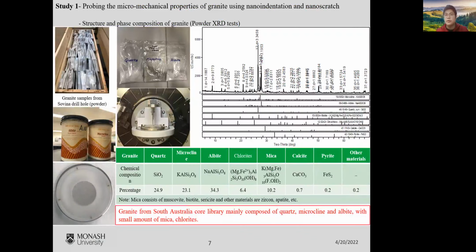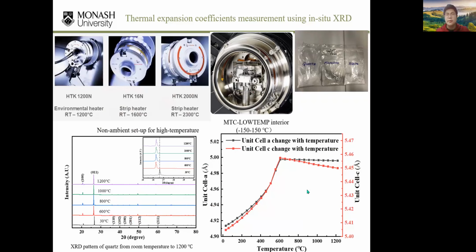Before we carry out nano-indentation, we need to obtain the structure and also the phase composition of the granite sample. Therefore, the powder XRD has been carried out. We found that the granite from South Australia, core library, is mainly composed of quartz, microcline and albite, with a small amount of mica and chlorite. Apart from the room temperature XRD, both high temperature XRD as well as low temperature XRD have been carried out. According to the in-situ XRD, the unit cell as well as the temperature-dependent thermal expansion coefficients of the granite rock-informed minerals have been extracted.